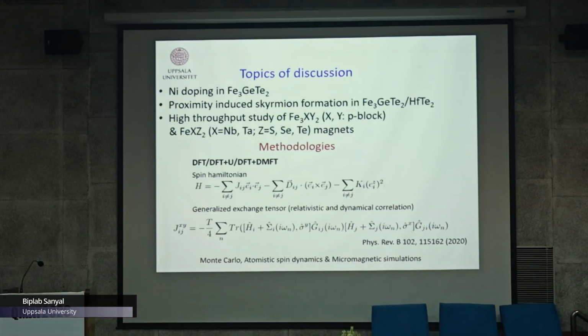So basically what we want to calculate is a generalized 3x3 exchange tensor, and in this tensor we can have the relativistic treatment included, and also if you want the dynamical correlation, that can be added on the same footing, and it is a closed form of this Jij tensor. This J tensor can be written like this, where you have both the self energy that is coming from the electron correlation, and then you have the spin orbit coupling that gives the non-diagonal part of this J tensor.